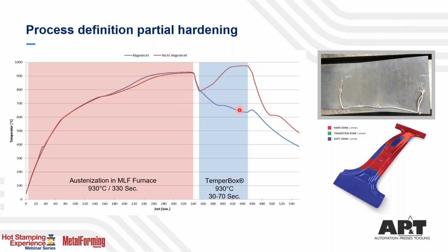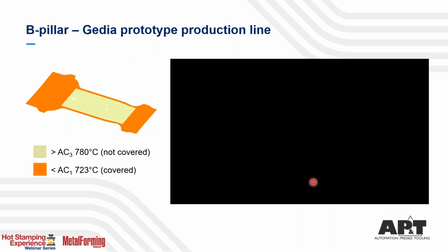And the other areas are actually cooled down, as I said before, with similar cooling rates as we would achieve if we did cooling on air. And you see this phase transformation here, roughly above 630 degrees. And close to, before we reach this area where we have the phase transformation, we take the part out of the temper box and transfer the part into the press, into the die, form it and quench it. And you would get those parts with very localized mechanical properties.